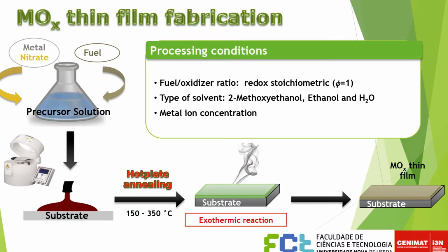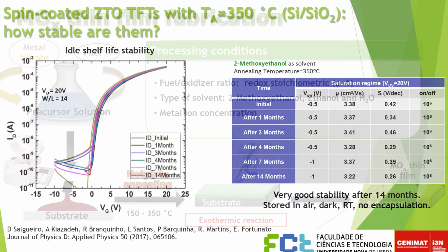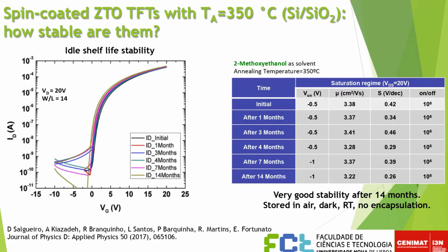So this is quite easy. We mix metal nitrate with the fuel in the precursor solution, we spin the solution on the substrate, and just by heating we will have our metal oxide thin film. Here are some examples on ZTO using this process. As you can see, even after 14 months the devices are quite stable, and in that case they are not passivated, so they are not encapsulated. And since we are using a bottom gate configuration, the semiconductor is exposed to ambient conditions.